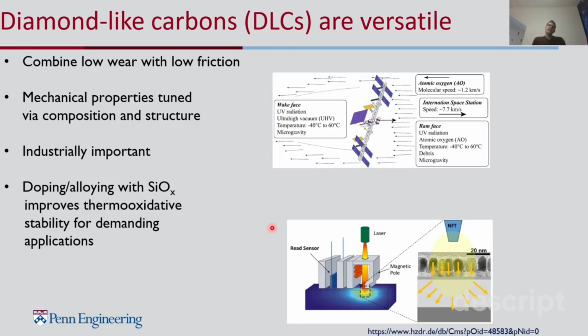Researchers have wanted to improve the properties of these materials for a long time, and one way to change the response of them is to dope them with various elements. And so the particular material I'll be talking about today is doped with silicon oxide. And this is known empirically, and not the reasons why. It's known that they improve the thermal oxidative stability of DLCs.